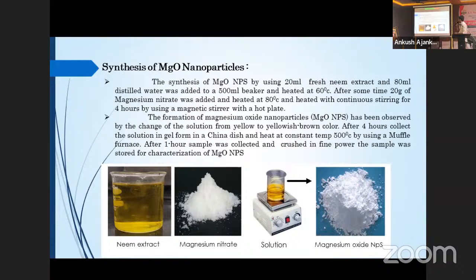After 4 hours, collect the solution in gel form using a china dish and heat it in the muffle furnace for 1 hour. After 1 hour, collect the sample and crush it into a fine powder. That is the stored sample of magnesium oxide nanoparticles.